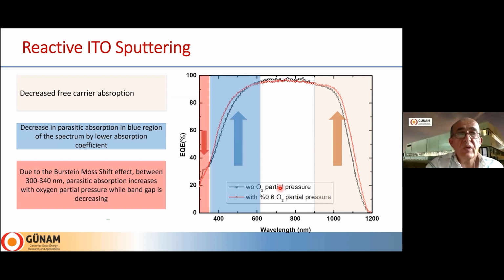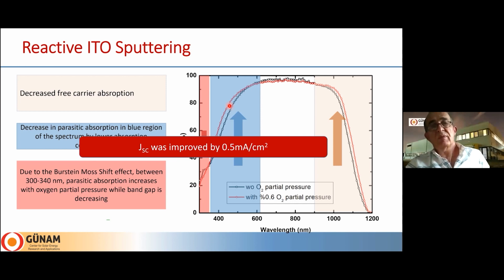So we have shown that by using reactive sputtering instead of standard sputtering, we have been able to improve the free carrier absorption. It means the parasitic absorption, and then we have improved the external quantum efficiency, as you see. Without any reactive sputtering, we have this black curve, but with some oxygen partial pressure, we have improved the external quantum efficiency values. We have improved the short circuit current by 0.5 milliampere per centimeter square. So this was another improvement in our heterojunction